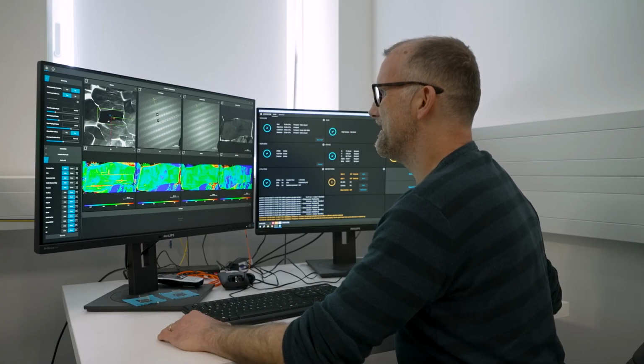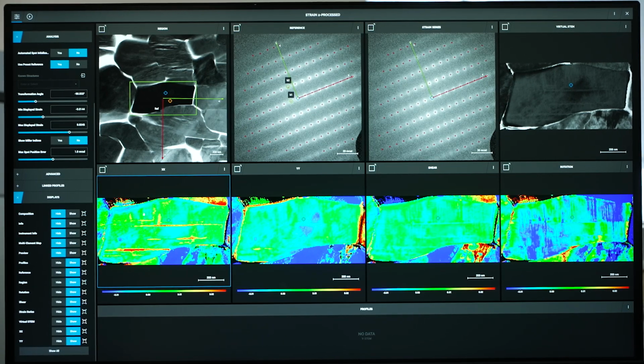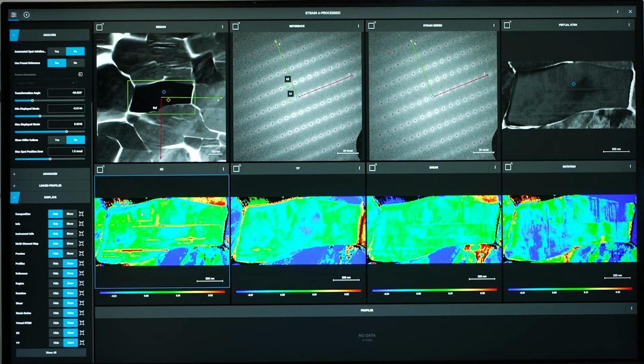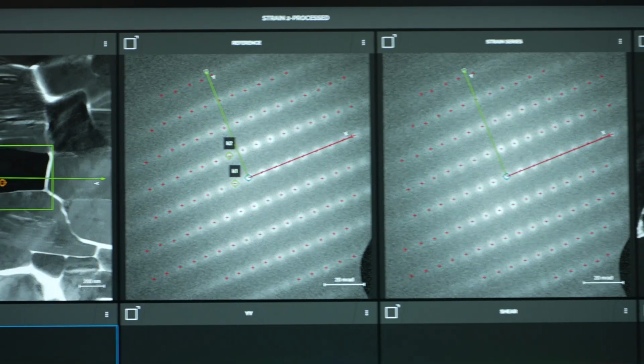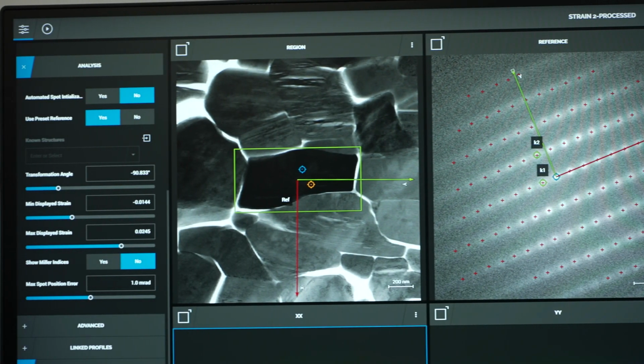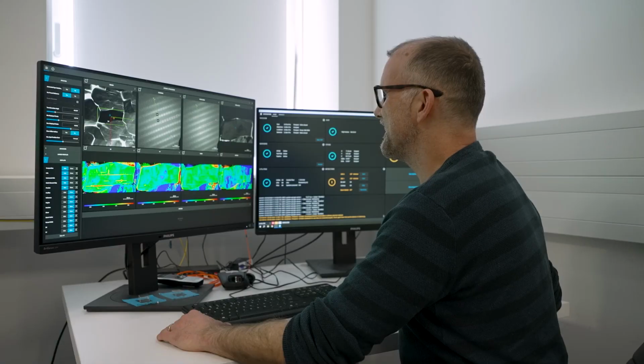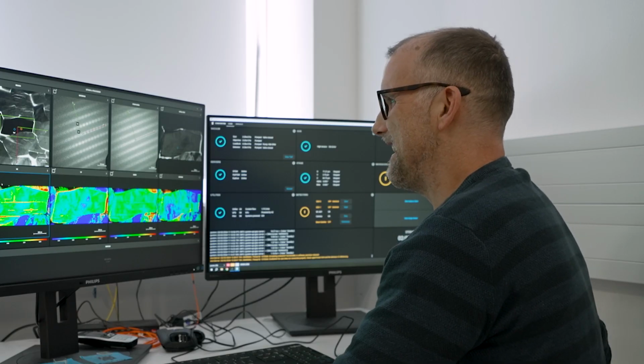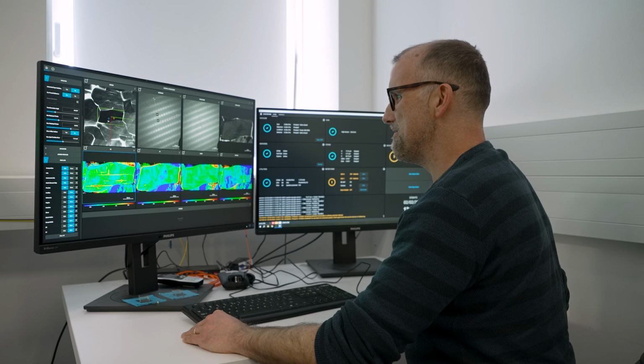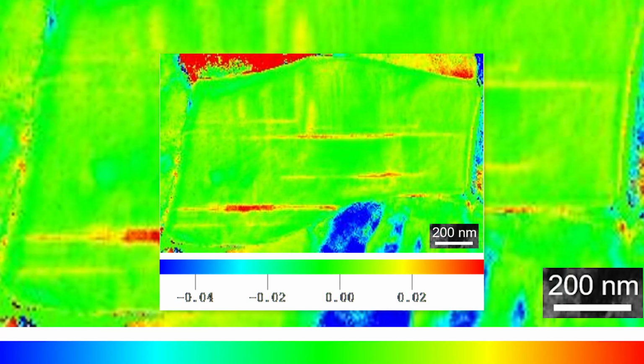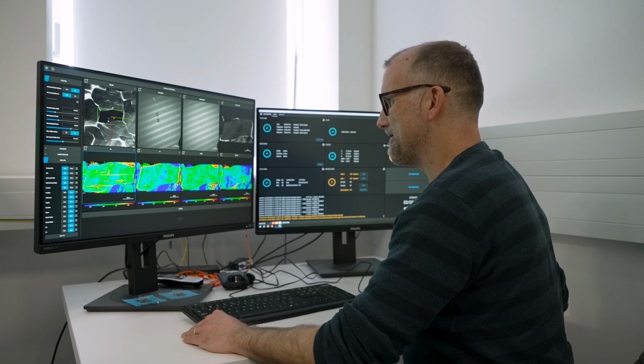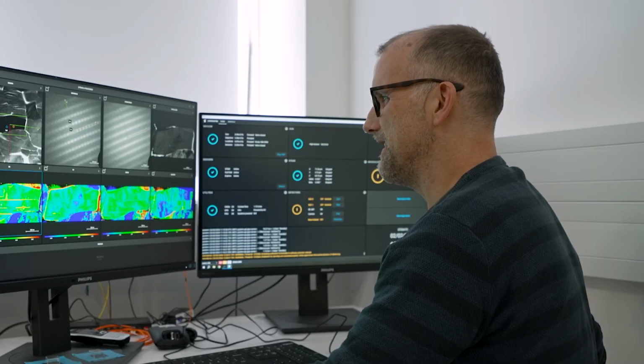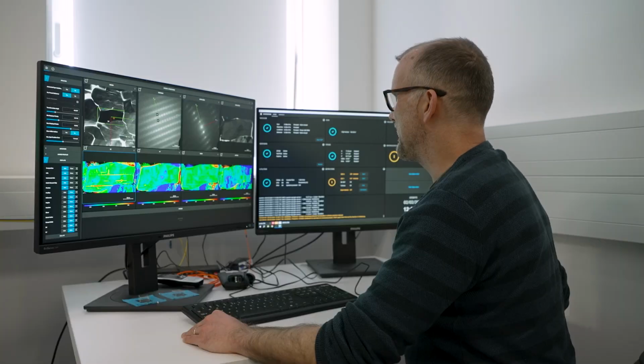So here we have an NMC sample, which is a layered lithium, nickel, manganese, cobalt oxide, which is used as a cathode, like an electrode in the lithium-ion battery. And within this layered atomic structure, the lithium ions are intercalated. So these results tell us where the lithium is intercalated into this particle, because the lithium ions need to diffuse into these particles to be intercalated, and features like the grain boundaries here could hinder the lithium ions from doing so and lead to battery degradation.